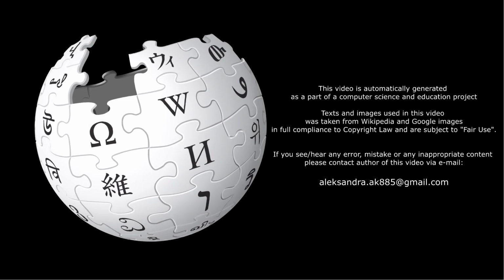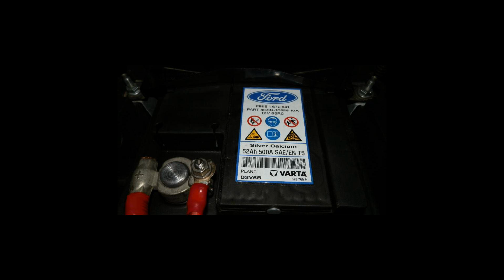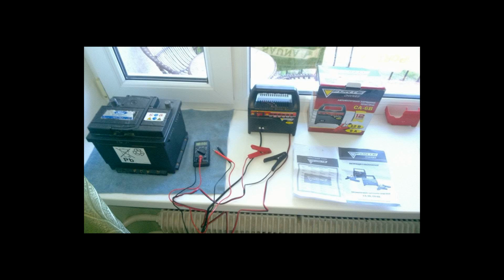The usual recommended charging method is constant current charging at a 10 or 20-hour rate, restoring the capacity of the battery over 10 or 20 hours, and cutoff of charging at 1.6 volts per cell. Cells are commercially manufactured from 2 to 2,500 ampere-hours capacity, but are often customized for particular uses.